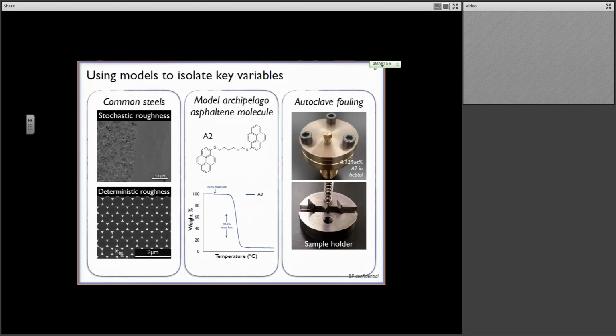These can either be these sorts of deterministic structures, or they can be pieces of our steel, and they sit at a vertical angle so we don't have a lot of gravitational deposition during this process. But either way, we put in this model or surrogate oil, we seal it up and we put it in our furnace. So that's our experimental approach.